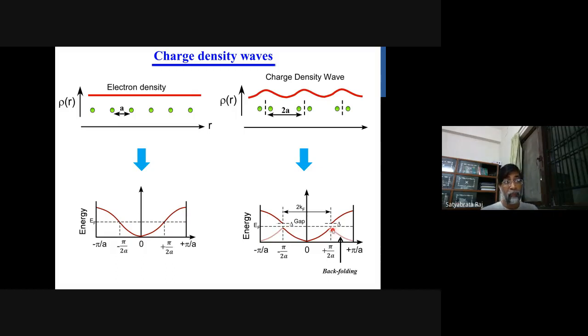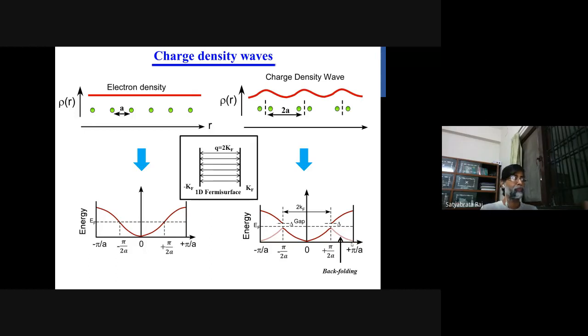And what is the signature? You can see the backfolding of the band, which can have very low intensity. So what is the consequence? In the metallic state, the 1D Fermi surface is a straight line. When there is a charge density wave, your Fermi surface will vanish. So to say anything regarding the CDW, the Fermi surface mapping is very important, and this Q is called the nesting vector, from one part of the Fermi surface to another part of the Fermi surface, and this Q should match with the